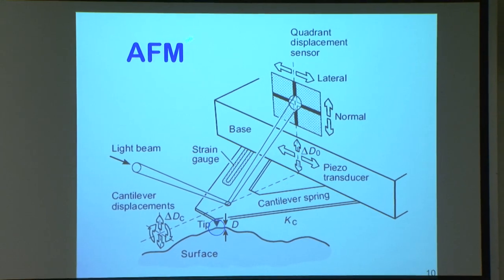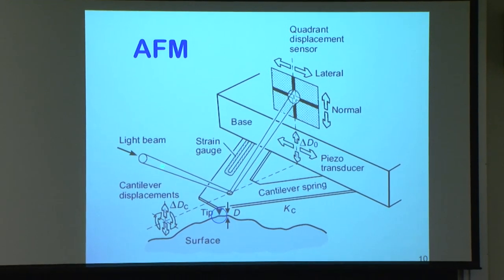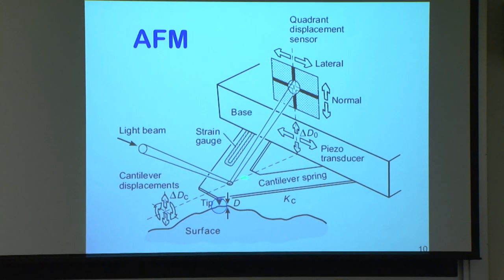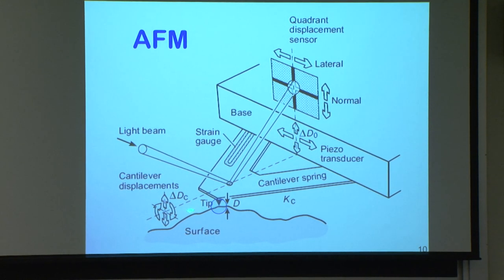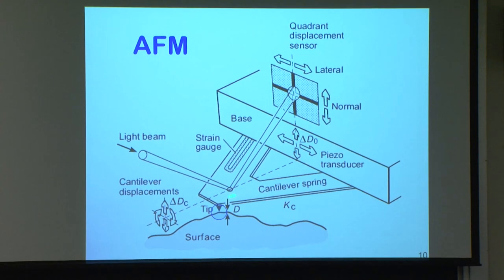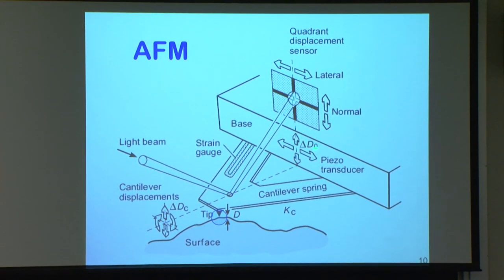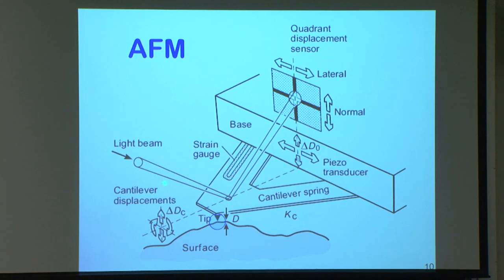I will also give some results with AFM. The AFM technique is also well known. The difference being that one measures the interaction between a tip or a colloidal probe, of small radius, much smaller than in the SFA, and the surface, and then scans the surfaces one way or another, and either using light or piezo-resistive elements measures the normal and lateral components of the forces as one moves the surfaces or scans across a surface.